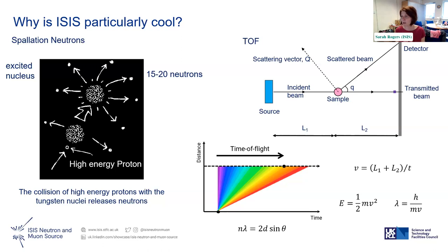But what that means is we still get a white beam. So even on a specific instrument, you don't get one wavelength, you get multiple wavelengths in one shot. And that allows us to use a technique called time of flight. Basically we know the distance from the source to the sample, and we know the velocity of those neutrons, so we can calculate the wavelength or the energy that you're interested in. Basically, you're getting multiple wavelengths in one shot, or multiple energies. So it allows us to cover a very big Q space without having to move parts of the instrument, such as the detector. So we don't have to vary theta, which is the scattering angle. We let the neutrons do the work.